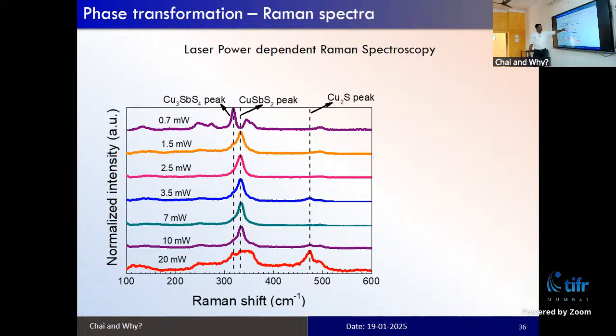Even at 1.5 milliwatt, the peak has shifted from here to here. This is 333, this is 317 centimeter inverse. As you put in more light, the intensity changes, and after some time, this further degrades and forms some other phase. You get a peak of some other phase. So basically, we changed the laser power from 0.7 to 20 milliwatt, and we have recorded the spectral changes.